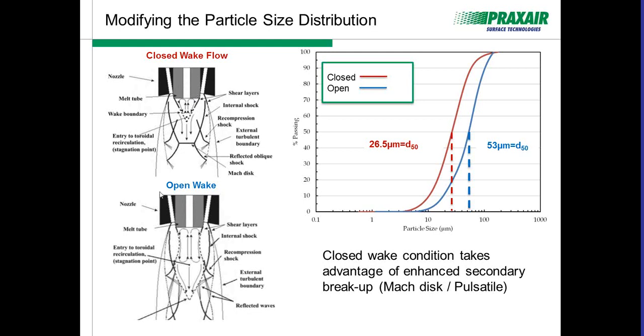In comparison, you can operate in what's known as an open wake model. This open wake creates a constant suction and more of a stable atomization process in which you're consistently and constantly pulling liquid out of the nozzle, driving it downstream, and simply shearing that liquid with high velocity gas. But it doesn't go through the two stages of momentary shutoff.